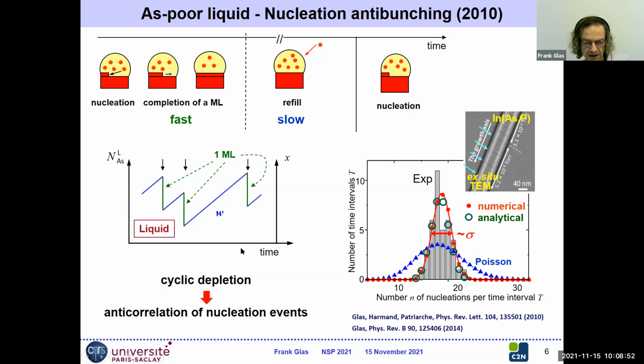And this we could understand easily using these schematics here, because when we nucleate one monolayer, if the monolayer forms entirely very fast, we deplete the liquid very fast of one monolayer of arsenic. So the concentration of arsenic decreases after nucleation and monolayer formation, which means that the chemical potential decreases as well, which means that the nucleation probability decreases as well, which means that just after formation of one monolayer, the nucleation probability is less than just before. So then we have this anti-correlation. The nucleation is less likely after the formation of a monolayer than just before. So we have this anti-correlation of nucleation events correlated with the cyclic depletion in arsenic of the droplet. And this we call nucleation anti-bunching. Nucleations tend to avoid each other. So that was the view 10 years ago.